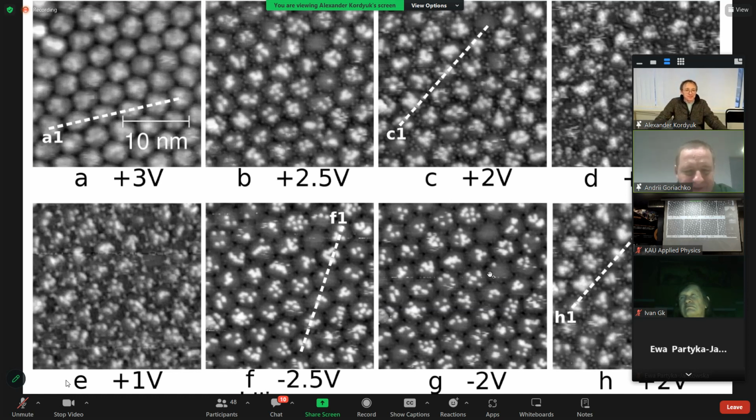When graphene contacts germanium in an atomically clean state, we have a very close contact of two lattices. One is the surface lattice of germanium, another of graphene, and they have different superstructure. As a result, the upper graphene layer becomes corrugated.